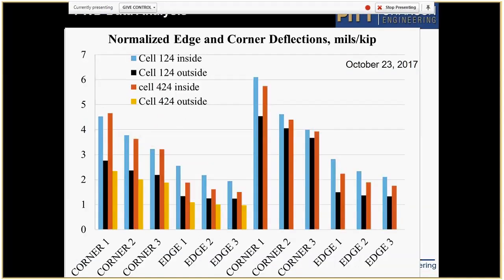And just a few more slides. One of the concerns we had was that early loading may damage joints. In this case, we analyzed the load transfer efficiency, and it's interesting that for the inside lane that was subject to traffic after construction until this testing in October, the load transfer efficiency was about 90%, which is slightly lower than we expected for a doweled pavement at this age. But basically, it's pretty good anyway.